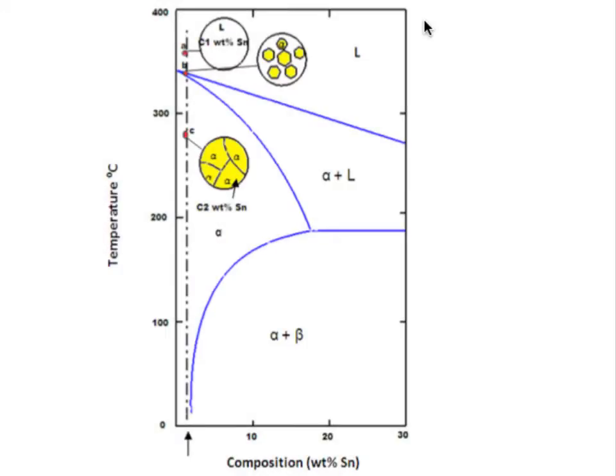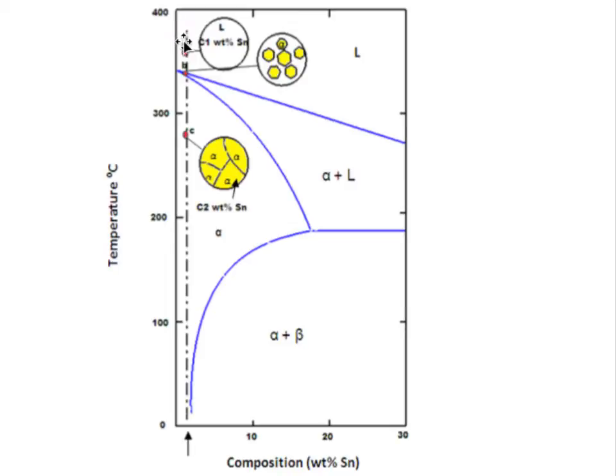Now we focus on the left side of the phase diagram for lead and tin. We see here that 100% lead is on one side, and along this axis we have the composition of tin. We can see the solubility lines for tin in lead at low temperature. We are going to see what happens when we have an alloy along this line — about 2% tin in lead. Starting up here in the melt, we then lower the temperature. When we reach the liquidus line, we start to solidify a lead-rich phase — solid lead.